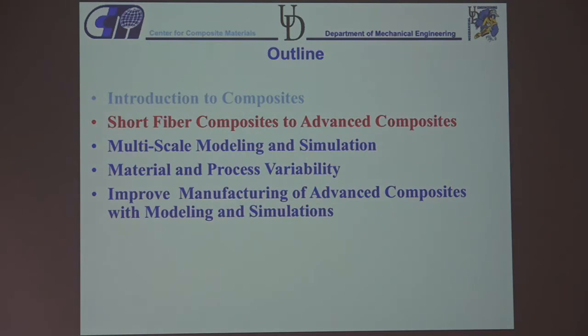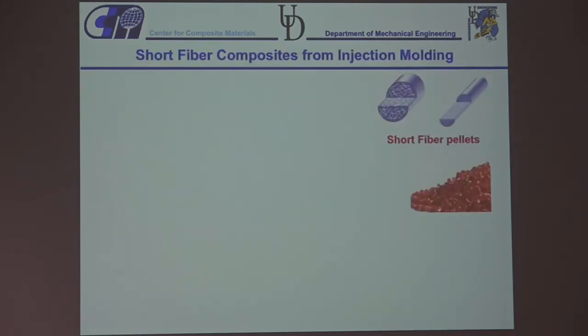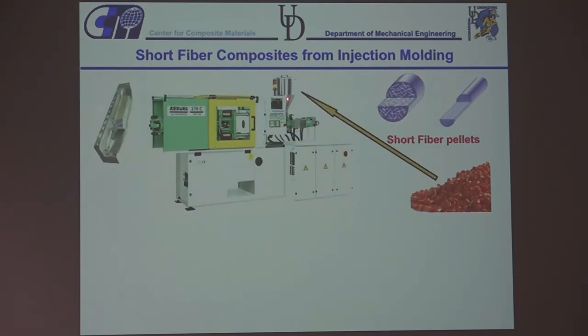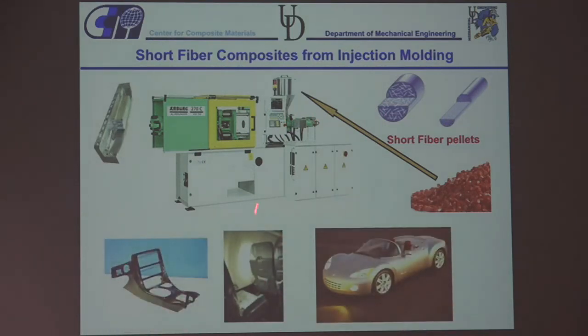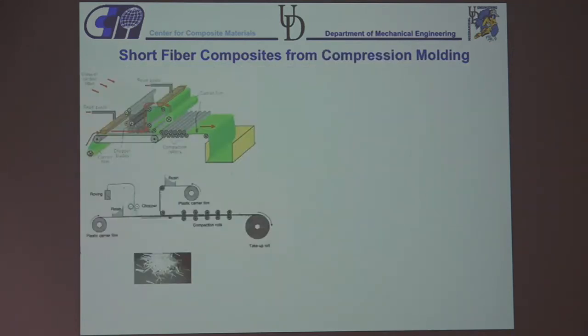So first the story about going from short fibers to continuous fibers. In short fibers you usually have pellets with short fibers embedded in them, and then you put those pellets into a hopper, and then they go through a screw and into a mold, and you can make parts like this. And the advantage of short fibers is it's basically based on polymer processing, so you don't have to change the machines. They're very fast. You can make parts in 30 seconds, 1 minute, and so that's the big advantage.